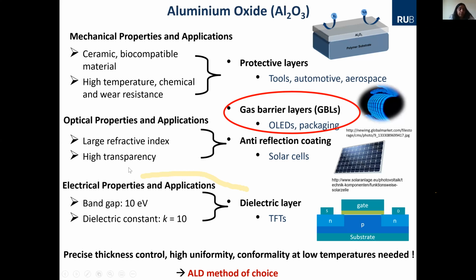Then it also has a very good refractive index and good transparency, so it can be used for optical applications, for example, in solar cells as anti-reflection coatings. Aluminum oxide as such is a very dense material, and when you have a very dense material, the seepage of water, oxygen, or moisture through this layer is minimal. So that's the reason it's used as a gas barrier layer. That means you do not let any outside atmosphere seep through into a device. Especially in LED TVs or displays, you see that the whole LEDs are packed by a gas barrier layer. That means you coat a very thin layer of aluminum oxide.